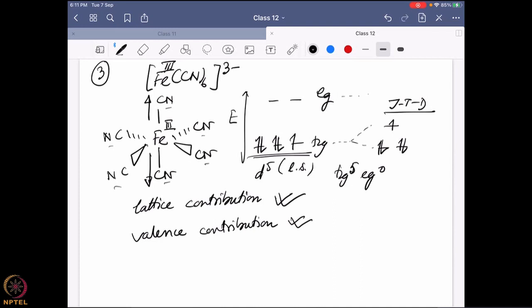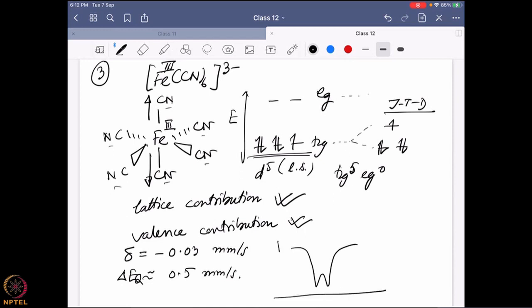And in reality, what we see is a delta value of minus 0.03 millimeter per second, and delta EQ value close to 0.5 millimeter per second. So you can draw this thing. This is going to be two very closely lying lines. And that is what is going to show over there. So now the first question is, where is the delta value? So what are you going to do? Take the average of these two lines and draw in the middle. And this is the delta value.